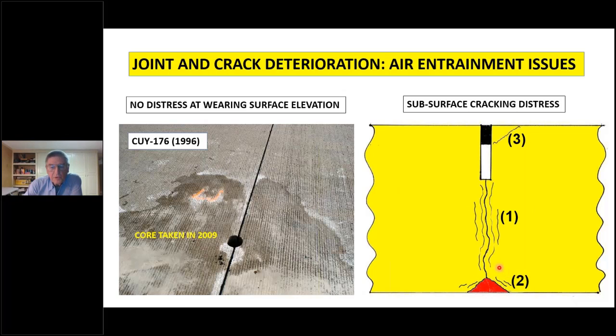Number two, we have the same sort of cone-shaped type of distress down here. That's commonly the way the D-cracking started off. And then when this is advanced enough, we lose the support here, of course, and we get the curling and traffic-induced loading up here, and so we get additional cracks that come off, and that's when you first begin to see the distress at the wearing surface level.